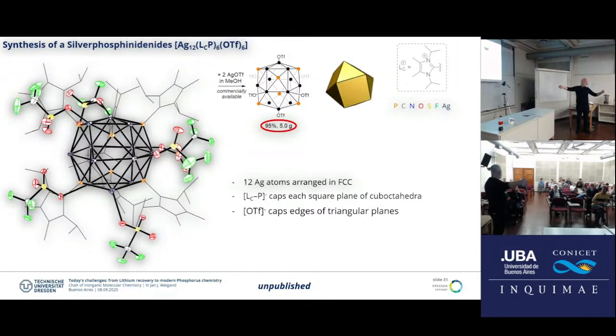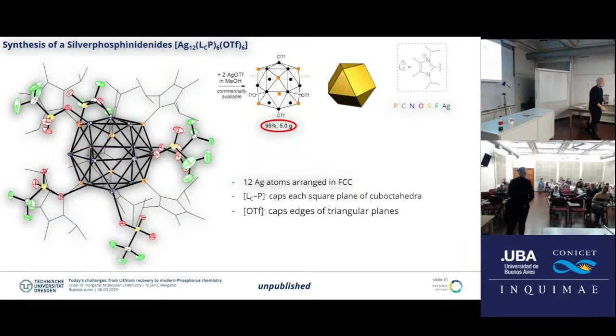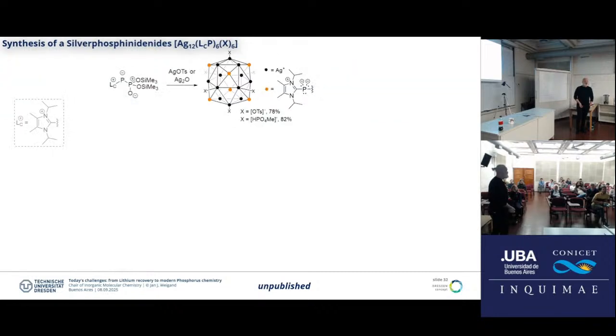LCP, our phosphinidene, which carries the negative charge, one of them. It's balanced by the positive charge of this one, so this is neutral, but 6 of the silver are formally cationic, so you need 6 triflate to balance the whole complex. Now, why is this interesting? Now you can also use different counteranions, the tosylate, for example. You don't use the triflate salt, or you can even use the silver oxide. And then the counteranion would be your phosphoric acid anion, which also coordinates to your phosphorus.